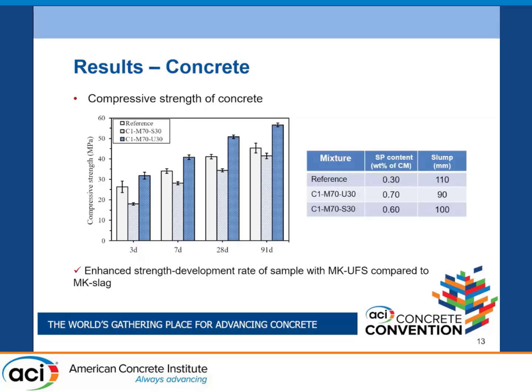The superplasticizer content comparison you can see here. Obviously, when we are using ultrafine slag and metakaolin, we need more superplasticizer content, but we can get a similar slump. It was almost double the reference sample, but it was similar to the one with the slag and metakaolin.